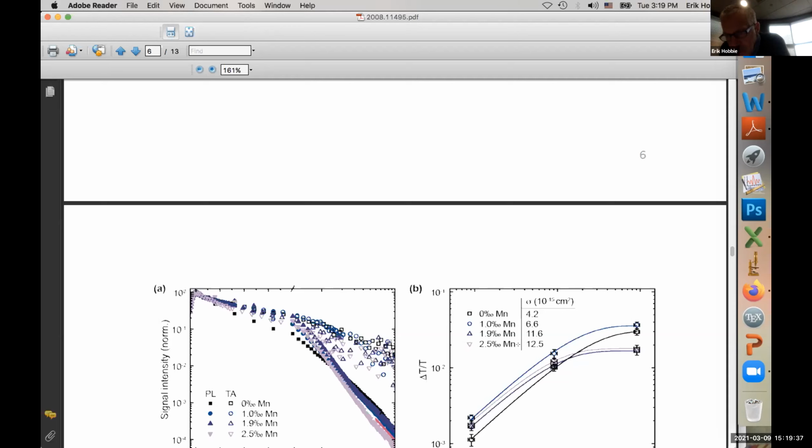Okay. Do you think it could vary by as much as a factor of 2? Because what I did was I looked at the absorption measurements of the fractions, comparable fraction number, so comparable size, as a function of the doping content of the parent. And what I saw was that the absorption tended to go up as the amount of dopant went up, which is consistent with this right here.